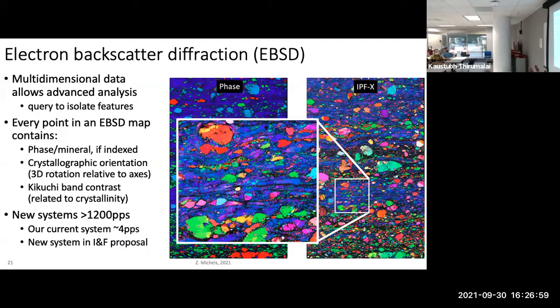What that's good for is you can actually not only get the orientation of a crystal at any point, but different minerals have different organizations of those Kikuchi bands. And so, through an image analysis that's built into the software that acquires this, you're able to index each point with a mineral. You have to tell it what minerals you think are in your rock, but EDS is really good for that, right? We can also hit it with the EDS and say, hey, I think we've got all these minerals in our rock. And you set that up as a list and you scan the rock and you can make maps like this. So on the left is a phase map that I covered with this inset, unfortunately. And over here is an orientation map.